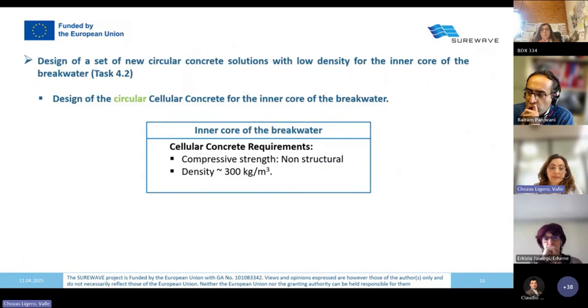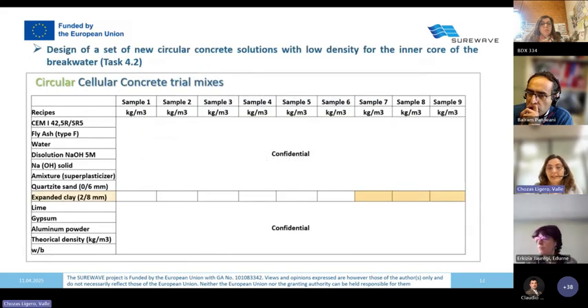The last concrete developed, for the inner core of the structure, was cellular concrete. There wasn't any requirement about compressive strength, but density was a high challenge, 300 kilograms per cubic meter. In this type of concrete, 26 doses were needed to optimize the cellular concrete. In the first samples, the materials used were those used in autoclaved aerated concrete.